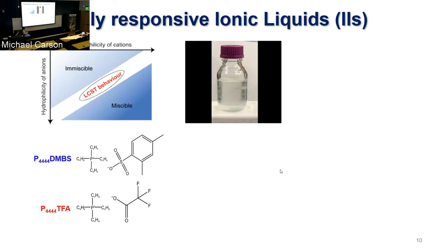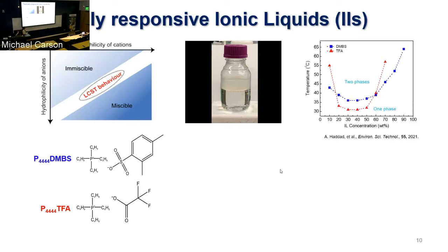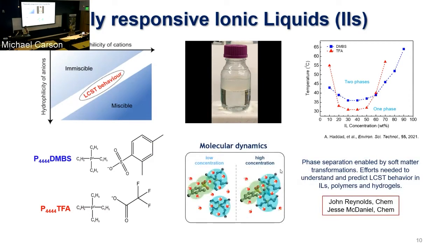So this is just showing you as we heat the material, you can see that it undergoes this milky transition. And then once it is fully heated, you can see it separating into two distinct layers with the ionic liquid and the water being those two layers. And it follows that phase diagram. So we're trying to understand how can we really design these materials to give us this critical transition behavior. And so this requires really understanding how the water interacts with the different functional groups in the ionic liquid. So here we're working with Jesse McDaniel's group in chemistry again, and they're doing some molecular dynamics in order to not only help understand, but also predict new materials that could potentially show this kind of phase transition.